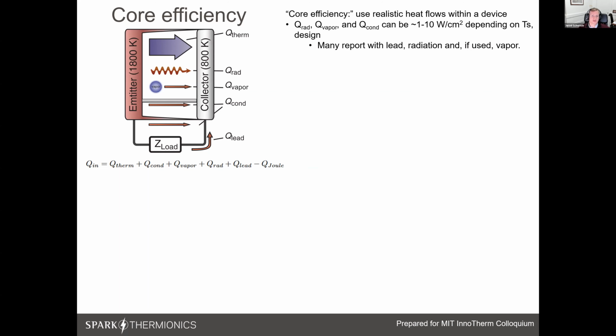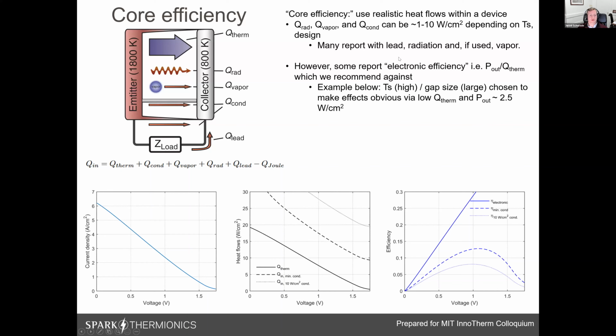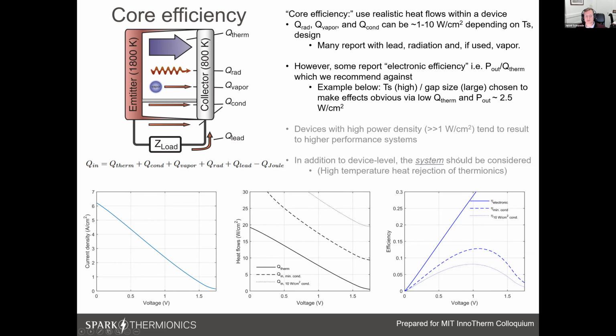And while many report this lead in radiation, some recently have started to report just an electronic efficiency. So ignore all of these thermal pathways and assume that electrons are carrying all of the heat from the emitter to the collector. And we recommend against this because we think that it overstates the potential and also points you in a direction towards a lower power density as opposed to a higher one. And so I won't go too much into these individual curves, but what you can see is that if you only focus on the electronic efficiency, you could be very excited about a, say, a 30% plus efficient device. And I'll just mention that these are typical IV curves for microgap devices, and we picked a 10 micron gap to exaggerate these effects. But if you look at what actually happens when you include radiation or vapor, you could be at 13%, if not below 10, once you consider these thresholds of these devices.